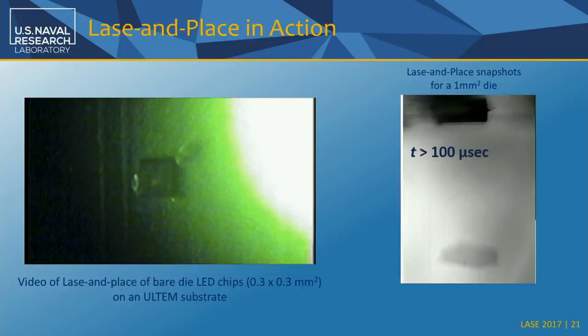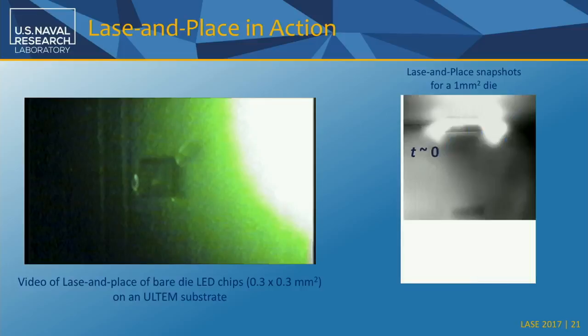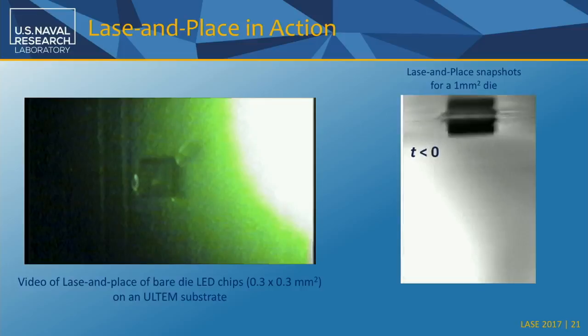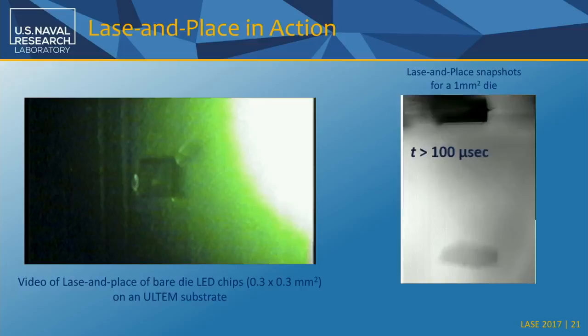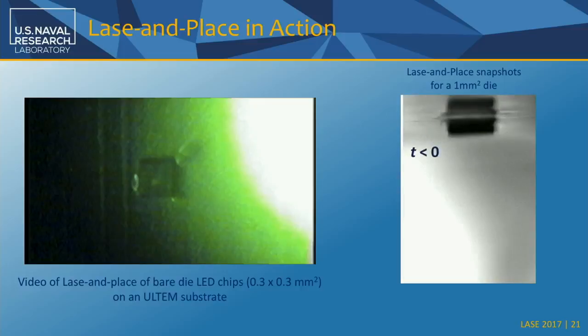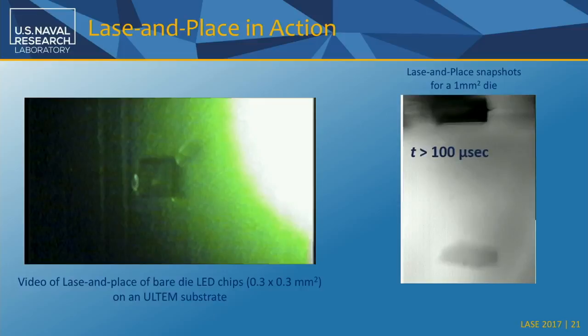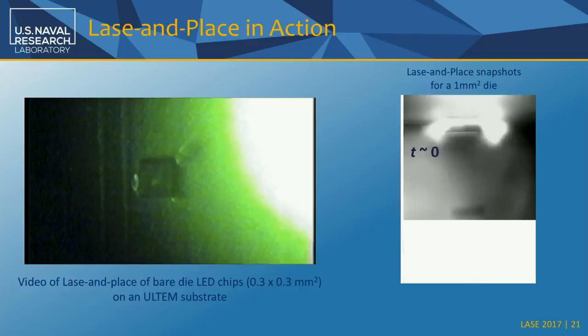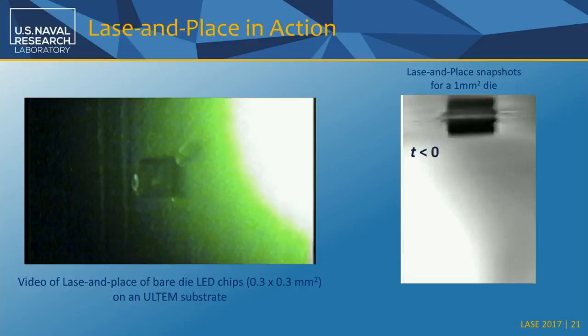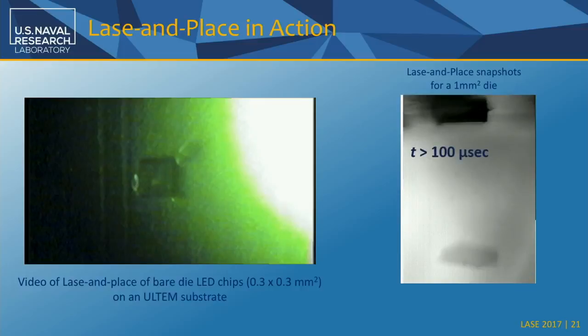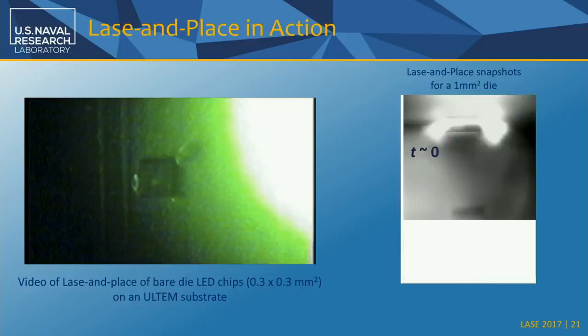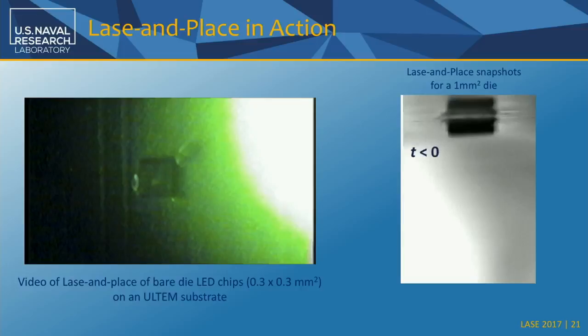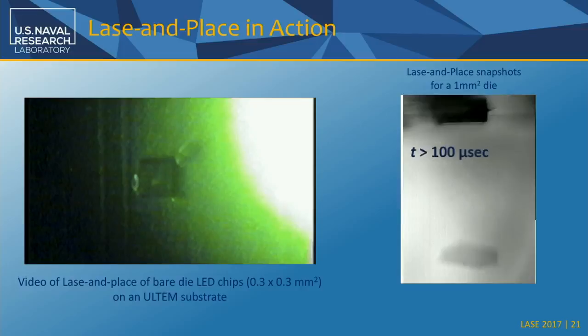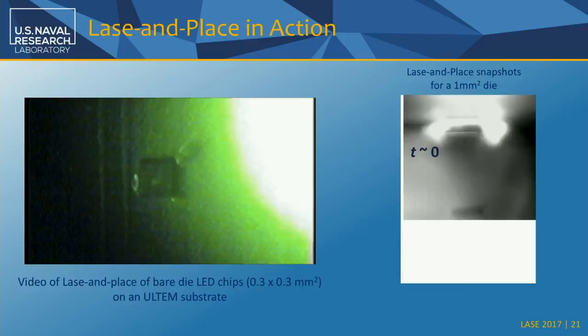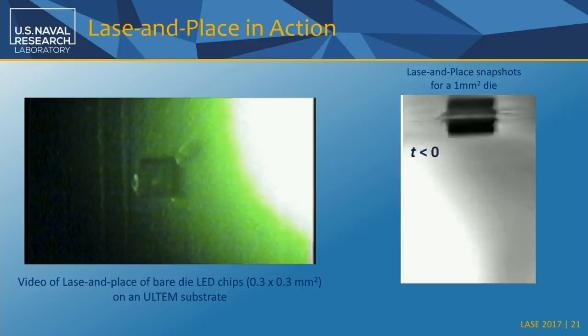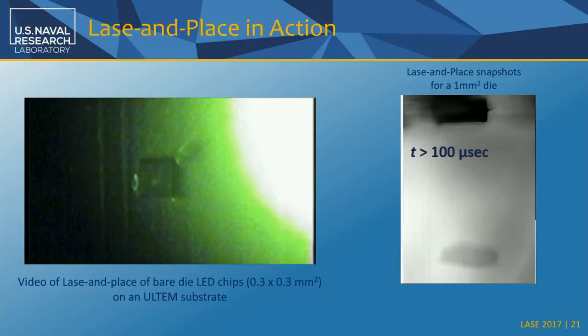And here I show you another frame-by-frame image of dummy devices. These are 1 millimeter square silicon chips, and you can see once the laser is fired, the chip flying away here. So there is the chip stock, the laser fires one pulse, and the device is flying away. One important thing to note is that this is a pretty thick piece of silicon because we just took a regular wafer, but we have actually shown that we can transfer devices or substrates that are as thin as 10 microns.